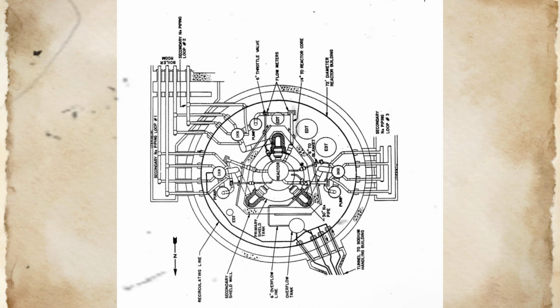The reactor's cover gas system provided continuous monitoring of volatile fission products that were released from damaged fuel and transported to the argon atmosphere maintained above the sodium coolant surface. This monitoring capability offered important information about the continuing rate of fission product release from damaged fuel, which could indicate whether additional fuel damage was occurring, or whether the release rate was decreasing consistent with successful stabilization of thermal conditions within the core. The cover gas monitoring data indicated that fission product release rates had decreased significantly following reactor shutdown,